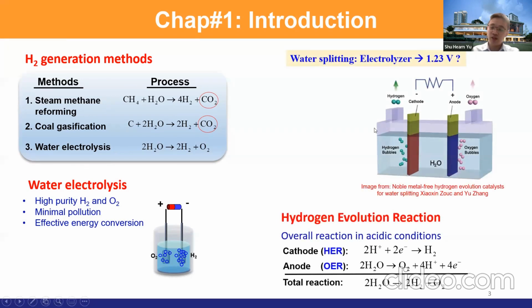This is the water splitting design called an electrolyzer. If you apply a potential above 1.23 volts, then you can generate hydrogen at the cathode and oxygen at the anode. Currently the state-of-the-art electrocatalysts are platinum for the cathode, and iridium oxide and ruthenium oxide for the anode. You can also insert a membrane here so that the hydrogen gas and oxygen gas cannot cross over, and you can get high purity hydrogen and oxygen.